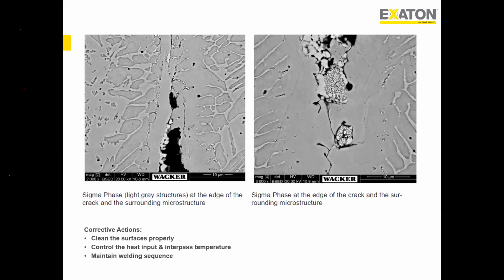So when they do the high cooling rate, it basically forms chromium nitride. But over time, as they went further and further with deposition, the cooling rate was getting slower and slower. And when the cooling rate got slower and slower, it started to form the sigma phase because the cooling rate was slow. So what was the mistake there?